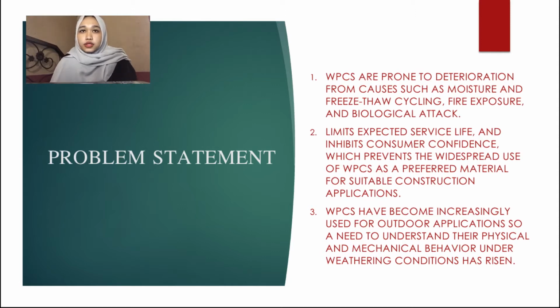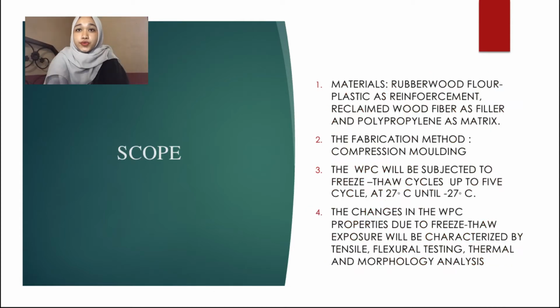Currently, in weather with freezing temperature in the presence of moisture, freeze-thaw-induced damage occurs in addition to moisture-induced damage in rubber wood floor plastic composite. The wood fiber reinforcement swells due to the absorption of moisture, and the absorbed moisture further expands upon freezing. Therefore, absorbed and consequently frozen moisture can cause damage in rubber wood floor plastic.